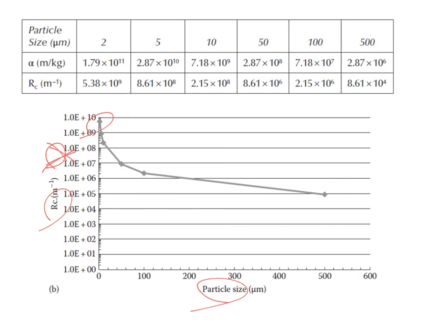And if we increase the particle size up to 500 micrometers, in fact, this cake resistance decreased by 10,000 times. So this is a huge decrease, which means if you just consider the membrane fouling and membrane permeability, the particles